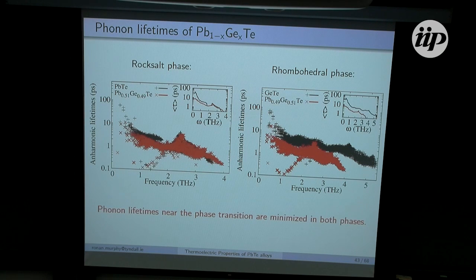And now I want to talk about what happens to the phonon lifetimes right on the verge of that. So I have here the anharmonic phonon lifetimes only. I'm excluding mass disorder for the moment. And I'll just take a moment to focus on the left-hand side of the slide. This is the rock salt phase. Lead telluride is in black. And this lead 51 germanium 49, again, which was chosen to be on the verge of the phase transition in the rock salt phase. And here we see we get quite a nice reduction in phonon lifetimes at lower frequencies.